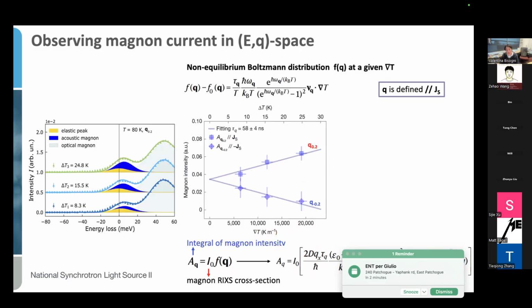We can then solve this equation by extracting these two missing parameters, where the most important and relevant one is the Magnon relaxation time at a specific Q. What we find is that the Magnon relaxation time at this Q is around 58 nanoseconds. So this value is in line with previous results found at Q equals 0, and assuming then a decrease of Magnon relaxation time for increasing Q. But other than that, there is really no knowledge about how the Magnon relaxation time should evolve with Q.